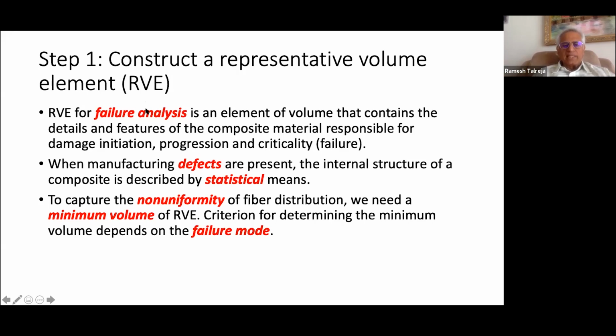But if you want to do failure analysis, where the internal structure should be representative of what manufacturing produced, then the RVE has to account for certain features of the internal structure which are important to producing the damage. And those defects that I talked about, non-uniform distribution of fibers leading to clusters, resin-rich pockets, they had to be in the RVE from the perspective of causing failure. So I'll illustrate to you how that is done.